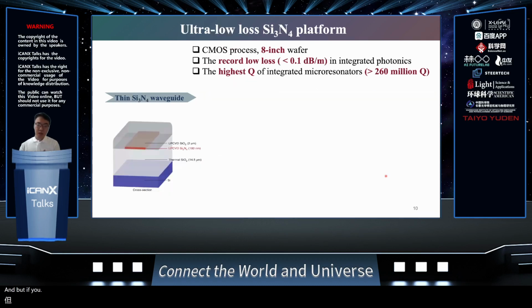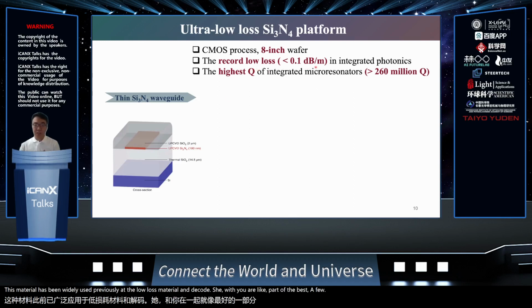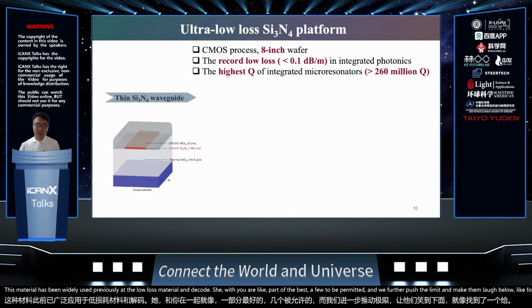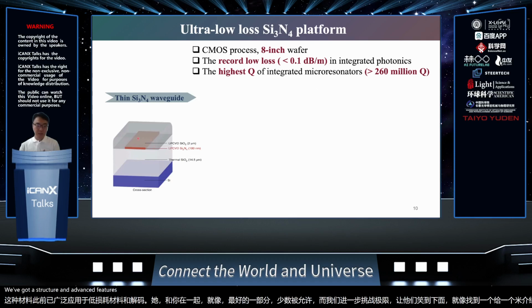But if you really want to push the limit of low loss, maybe silicon nitride is a better platform. This material has been widely used previously as a low loss material, and it can achieve at best a few dB per meter. We further pushed this limit and made the loss below 0.1 dB per meter by introducing a novel waveguide structure and advanced fabrication technologies.